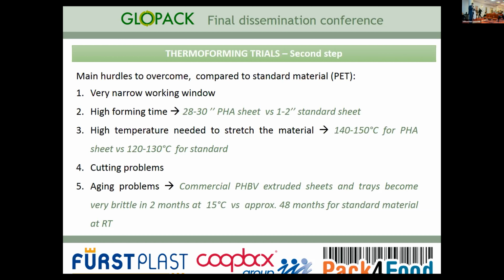We made a comparison with PET, which is a common material used for thermoforming of trays. You can see we have a very high forming time, half a minute, 30 seconds more or less, and a high temperature. This means that if you want to put this material in an industrial production, you have a very low speed of production, and also a very high consumption of energy, because you have to use a higher temperature.